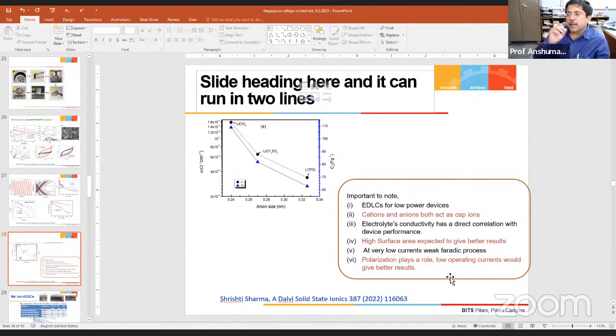So in batteries, we have seen that only cation should play a role, because cation takes part in the chemical reaction, be it sodium or lithium. But in supercapacitors, both the ions play a role here. Anions and cations both have to play a role. At one electrode anion is going to play the role, and at the other electrode you have cations playing a role. So you have to be very careful in choosing the ions.